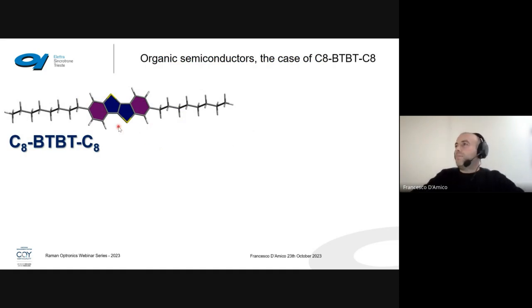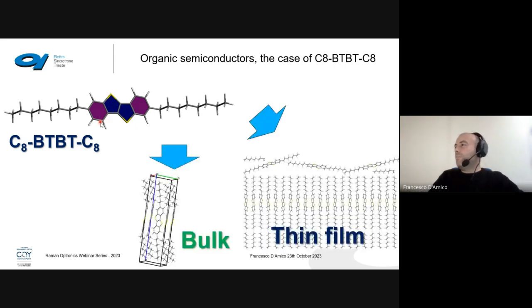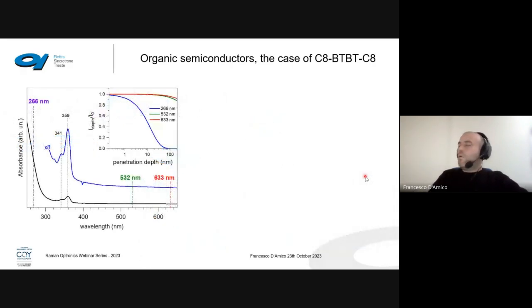This is an organic semiconductor. It is used to make devices such as solar cells, but to study the chemical conformation of this film, we should have a way to investigate the thin film, because in the bulk we know the structure also from XRD, but for thin films, in particular on the surface, we don't have any way to understand how these molecules behave on the surface from the chemical point of view. What can we do? We exploit resonant Raman.